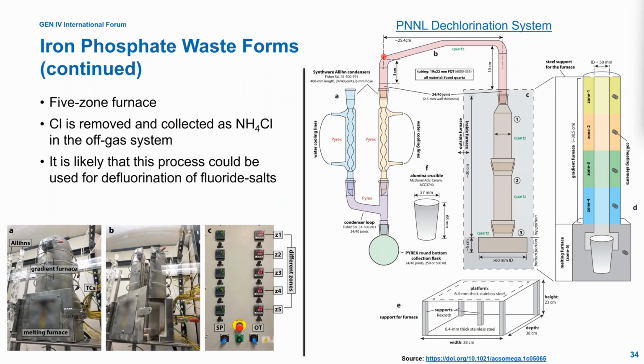The off-gas line is connected to a set of condensers to condense any liquid products that come through into the collection flask. And the ammonium chloride that comes through from the reaction in the crucible gets condensed in the glassware so that I can recover the ammonium chloride. And we've had recoveries up to 97% mass balance. So this is a pretty neat little system.